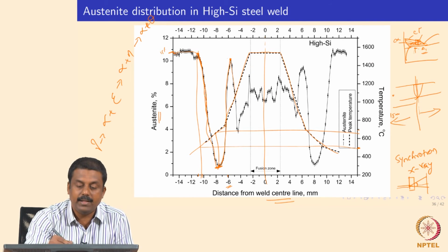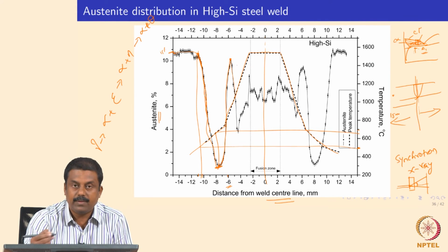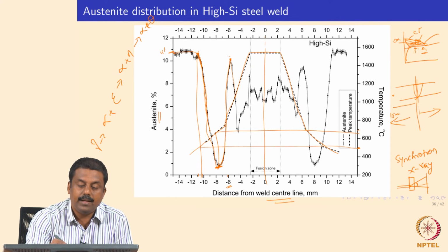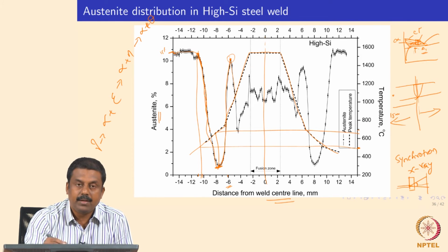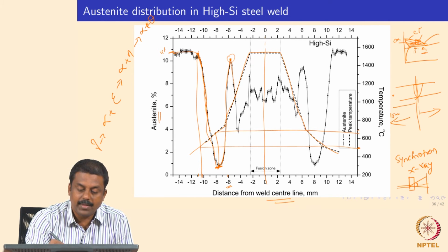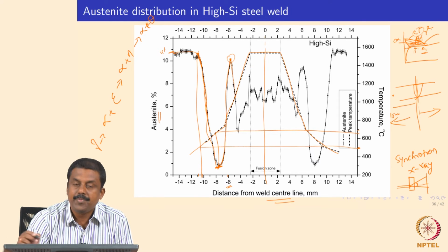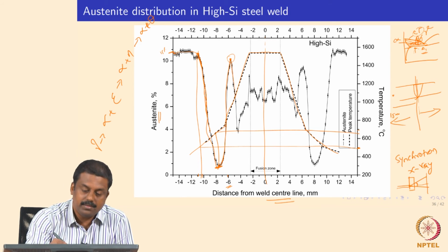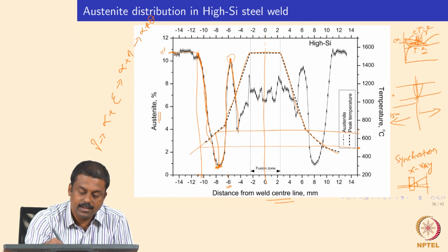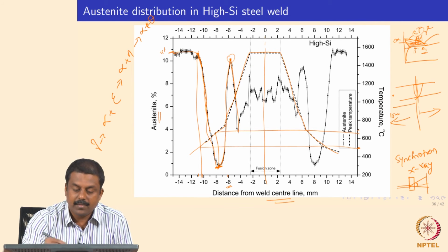Okay, and when the temperature reaches an intercritical temperature where both ferrite and austenite are coexisting, you will have an optimum partitioning of carbon to the austenite, which can lead to an increasing fraction. So, if you further move above the A3 temperature, what will happen? You will have a single phase austenitic microstructure, and then again there is no partitioning, right. So there is no partitioning, which means the fraction will decrease continuously when you reach a fully austenitic microstructure.